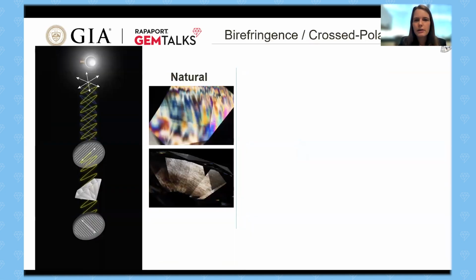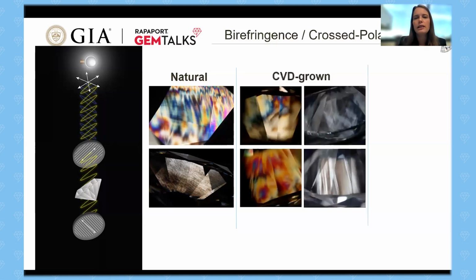Now, what if you look at your diamond between cross polarizers and look at the strain patterns, the birefringence patterns? For natural diamonds, they have had this very stressed environment down there in the depths of formation and in their residence. So typically you're going to observe different types of strain patterns, oftentimes with very strong, colorful colors, but potentially some more subdued tatami or cross-shaped patterns. If we look at the CVD grown, because there has been such a change over the years, you might actually see patterns that are really quite similar to what you observe in natural diamonds, so not very helpful.